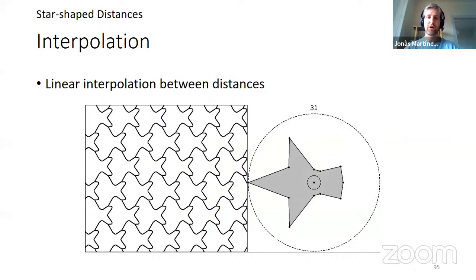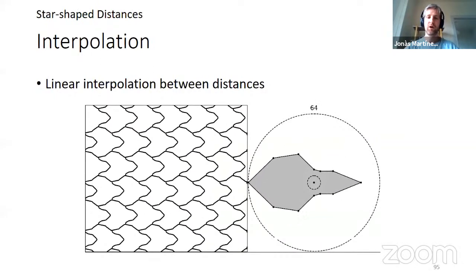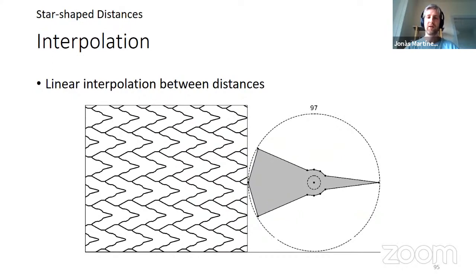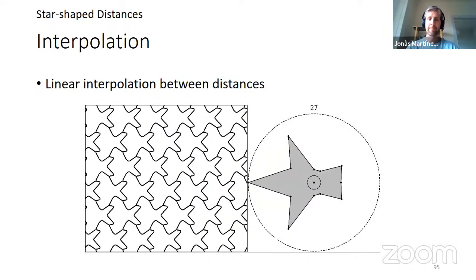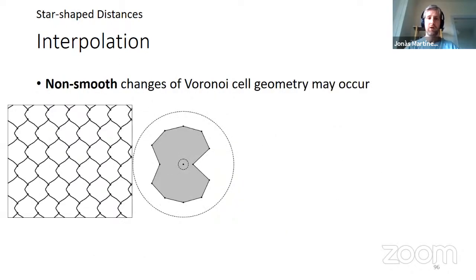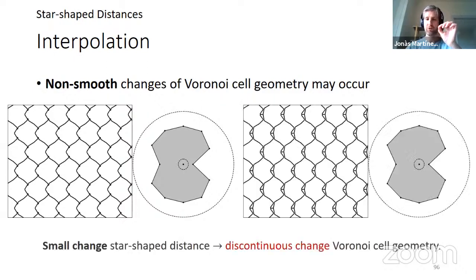Here you have a video of what's going on when you do linear interpolation. So you can see how it subtly changes from one tiling to another. However, I want to say that you can have abrupt changes. What I mean by that is that when you do this linear interpolation, you're not guaranteed that a small perturbation won't cause a discontinuous change in the Voronoi geometry. So here you see there are two star-shaped sets that have almost the same geometry, but there's a slight change, and abruptly there's a big change in the Voronoi. So that's something to study in the future.